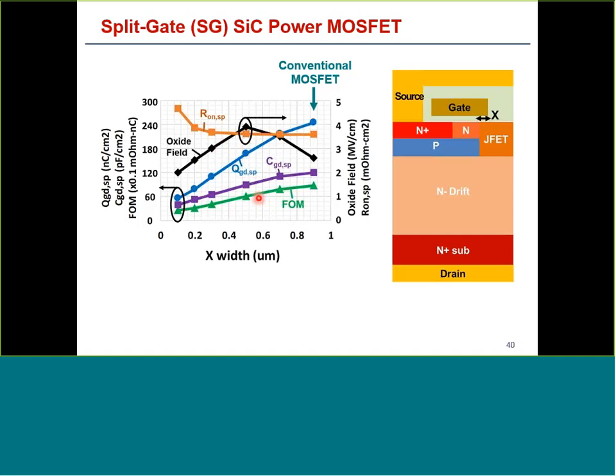But we have to also monitor the RDS on and the oxide electric field. So in terms of RDS on, as X is reduced, the accumulation layer at the top of the JFET region becomes smaller, and the RDS on does start increasing, so we have to be careful about that. And we have to also worry about any electric field enhancement at the edge of the gate. And you can see here that we have monitored it over the various values of X.